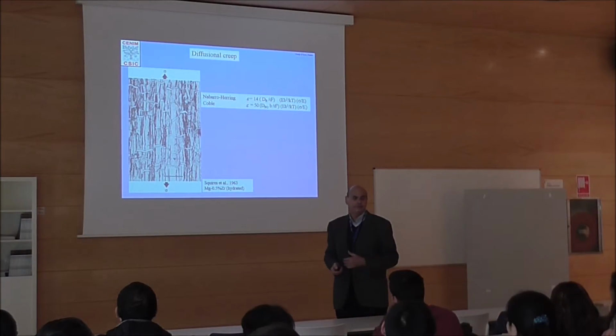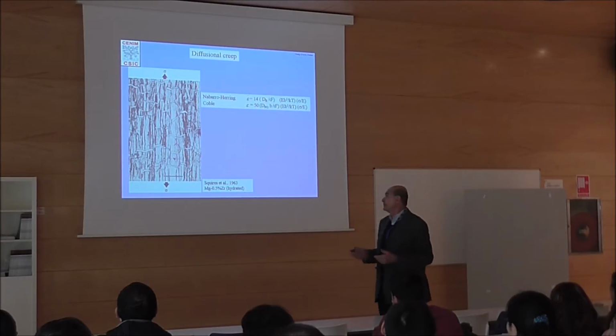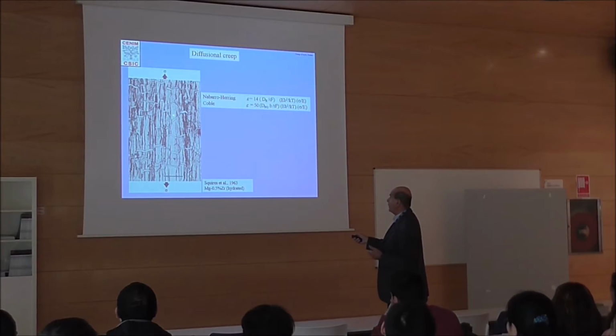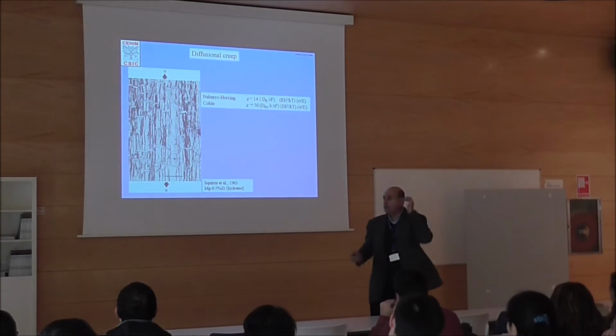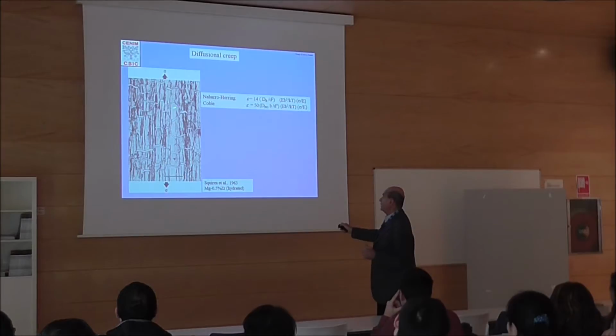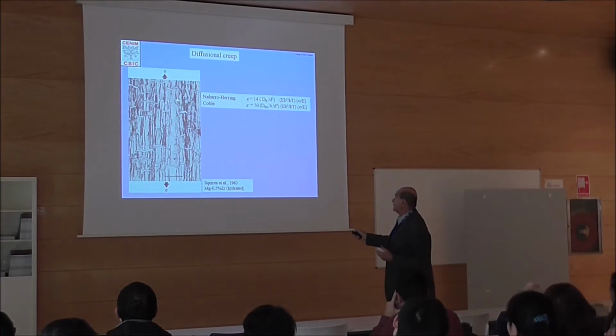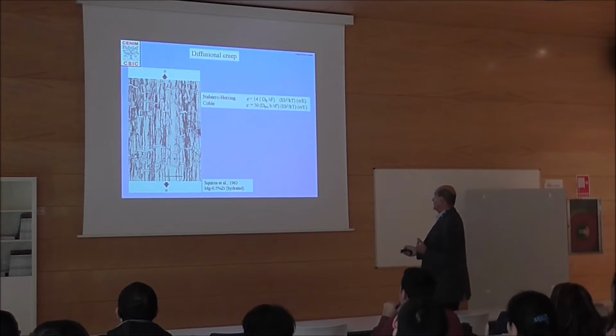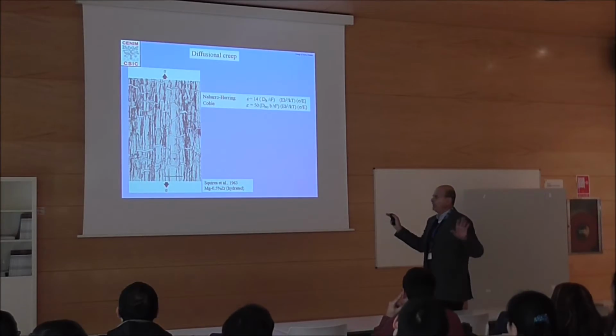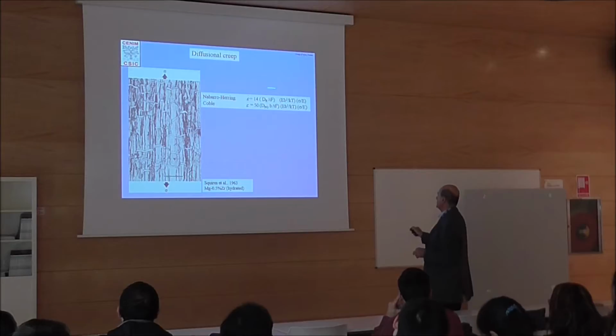It's very well known, in every single textbook you have denuded zones in the material. And this is because of this flow of atoms from this boundary that is subjected to tension to this boundary that is more free. Here is compression, and here we will have tension. So this means that magnesium, by diffusion, has gone from this boundary to this boundary. And then he developed these equations just by pure thought. There is no fudge factor, nothing assumed. That's wonderful, as I mentioned, a wonderful theory. And he develops Nabarro-Herring here.